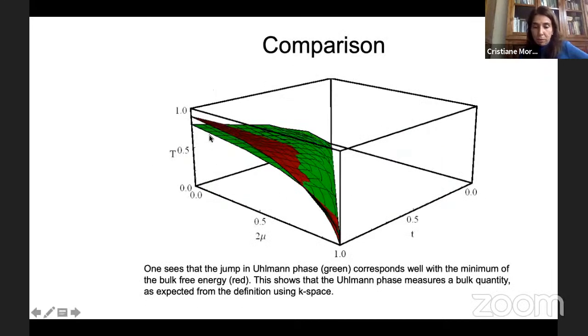When we do this for the bulk, we get a red curve, plotting temperature versus mu versus hopping. I get a red curve, and in places where you don't see this red surface, it's because it's overlapping with the green one. The green curve was obtained by Viyuela and Martin Delgado in their calculations of the Uhlmann phase for the Kitaev chain. Our red curve is precisely on top of it. The only thing we are doing is tracing the minimum of this response function as we move away from zero temperature. That's quite amazing, because we don't need to evoke anything else.